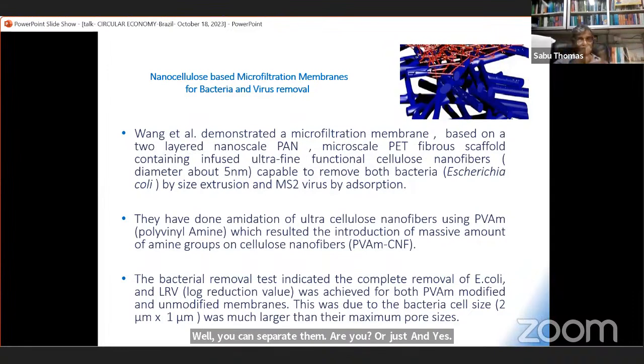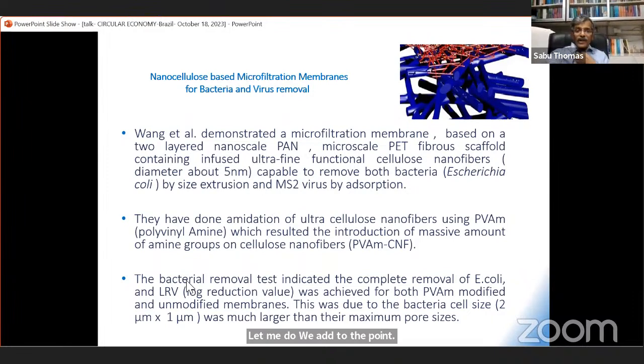So viruses are difficult to separate. What we do is some chemistry. We react with polyvinylamine. When you react with polyvinylamine, you can introduce massive amine groups on the surface. And then you can have electrostatic interaction between the positively charged amine groups and the virus. So this way you can remove viruses.